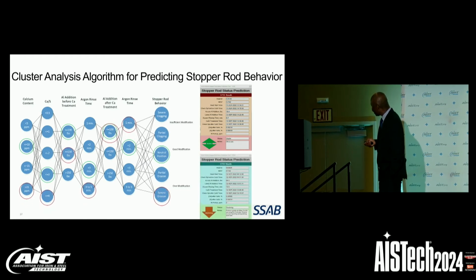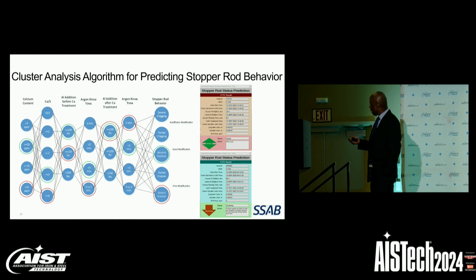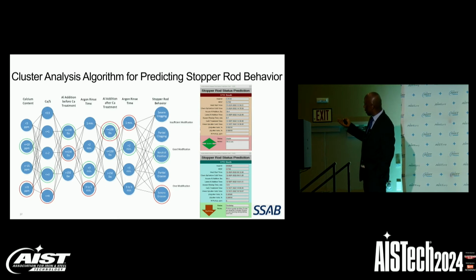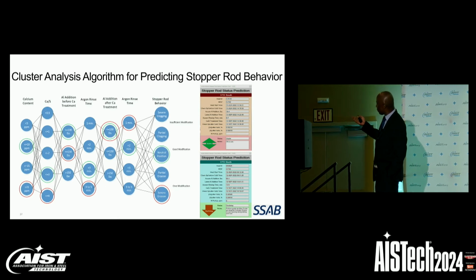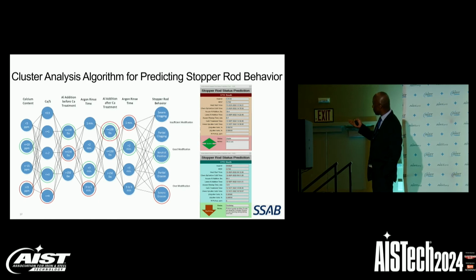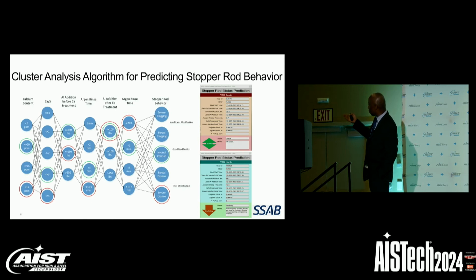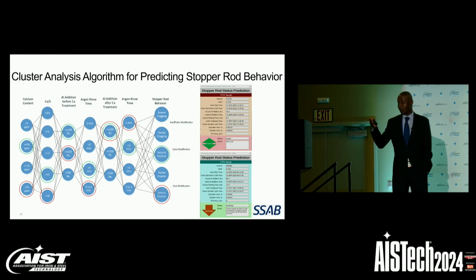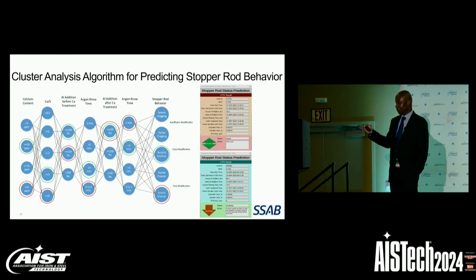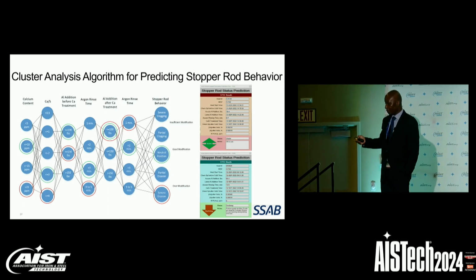When you compare it to another heat that ended up with a calcium of greater than 15 ppm and calcium to sulfur ratio of about 4, aluminum addition before calcium treatment of 150 pounds, argon rinse time of about 3 to 5 minutes, aluminum addition after calcium treatment of about 100 pounds, and argon rinse time of about 1 minute. This combination of process variables will lead to severe stopper rod erosion.